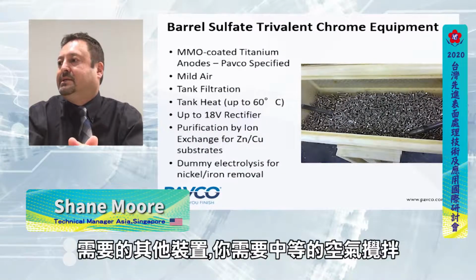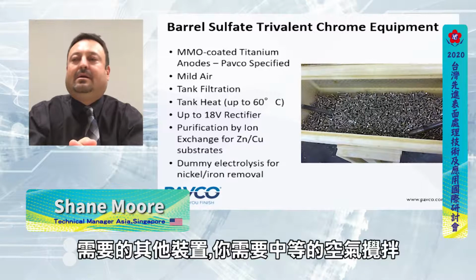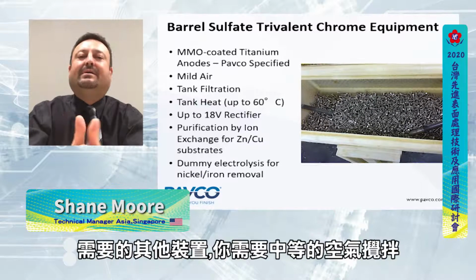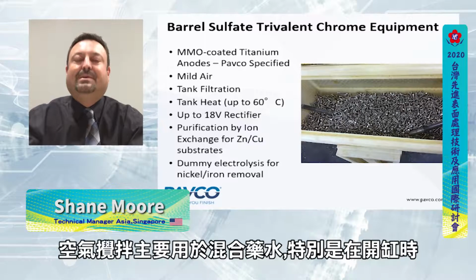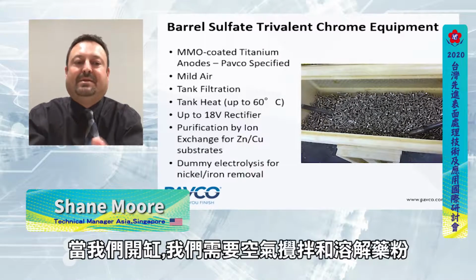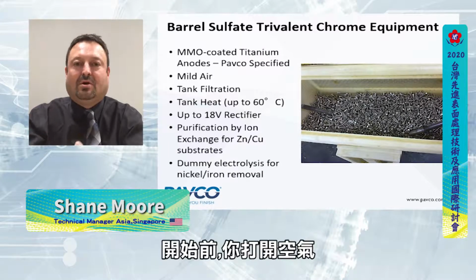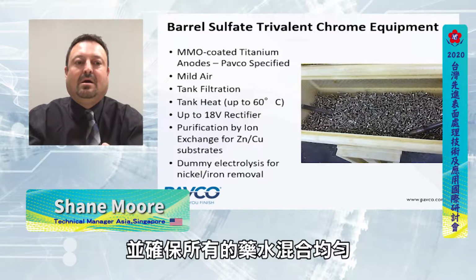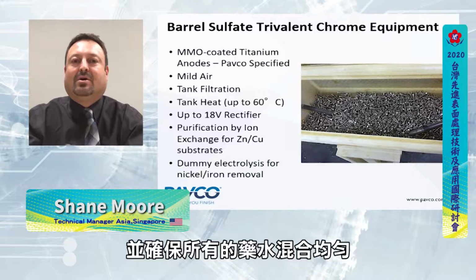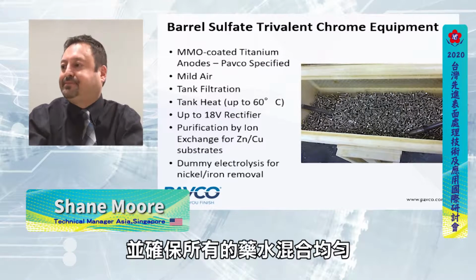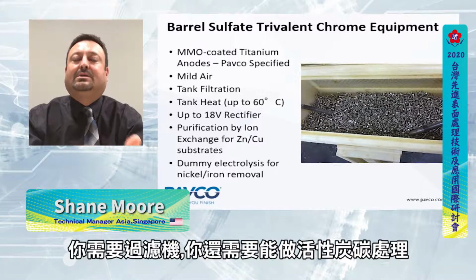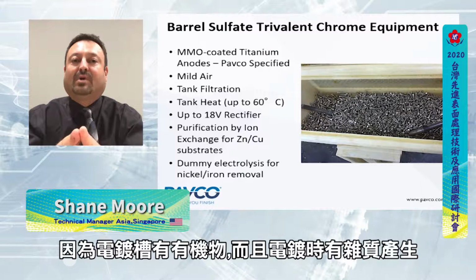Other equipment that's needed: you need mild air, mainly to mix the chemistry, especially in makeup. When you make it up, you need that air to help circulate and dissolve all the chemistry. Before startup, you'll want to turn the air on just to mix and make sure that all of the additives are homogeneous. You also need tank filtration, and the ability to carbon treat because the bath does have organics in it.